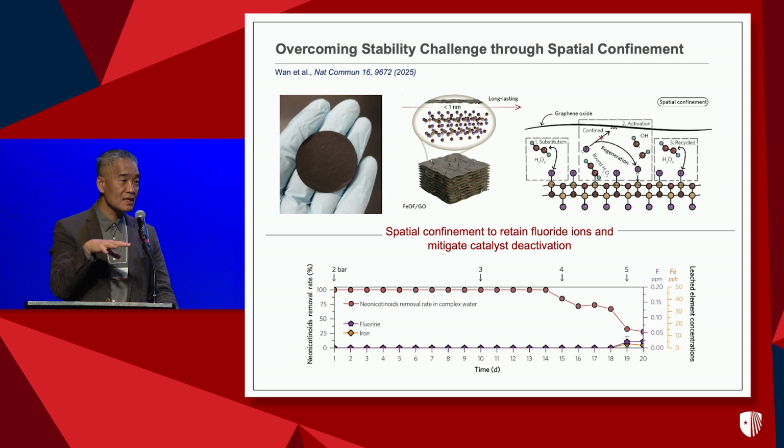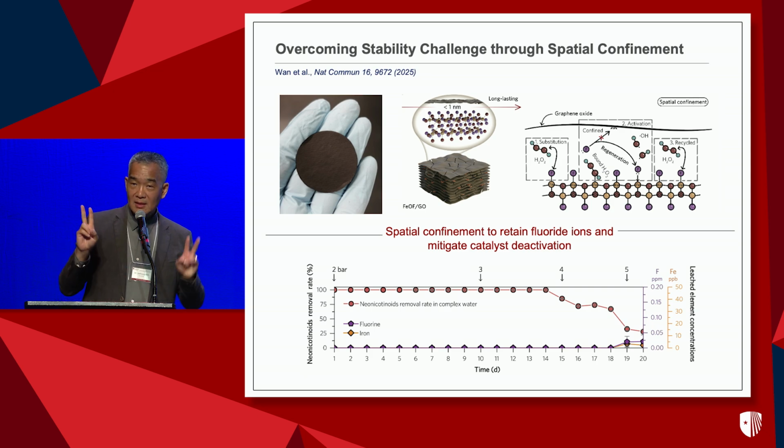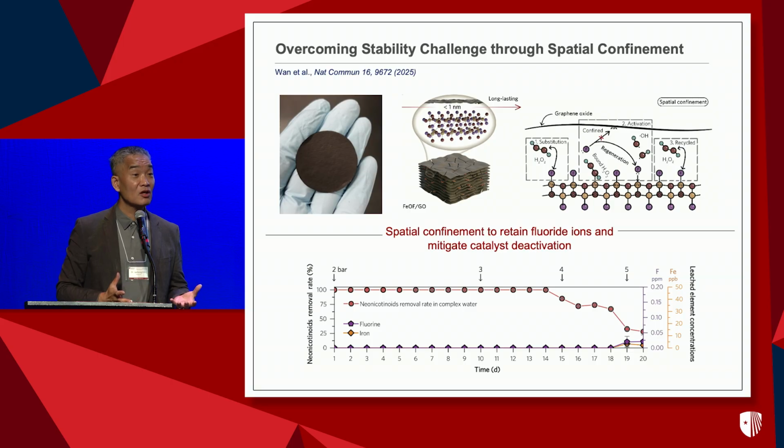And it seems like all the catalysts that we are working on are nano catalysts. If you have a nano-sized catalyst and if you have a pore less than 1 nanometer, what happens? Your pore gets clogged. It's no longer a membrane. So if I want to have a membrane with really, really small pores, but I want to have this catalytic property, how small should the catalyst be? Less than a nanometer. What is the theoretical limit of the smallest catalyst?